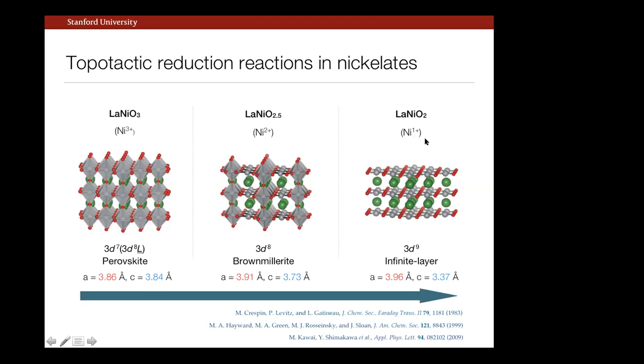So these are generally understood to be metastable compounds. There's no known way to access them in some sort of thermodynamic synthetic technique. Rather, you're using the scaffolding of the perovskite precursor phase to stabilize this cascade of reduction reactions and maintain the crystal structure. This was first discovered in 1983 using hydrogen gas as a reducing agent. There was quite a lot of struggle in a small but active community because it was very difficult to reproduce. There were lots of controversies actually about the reality of these phases.